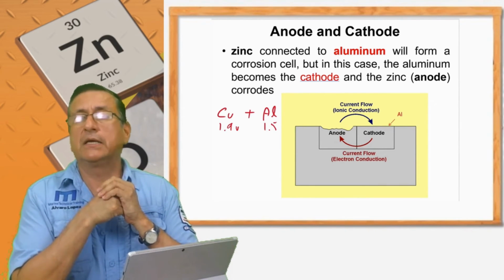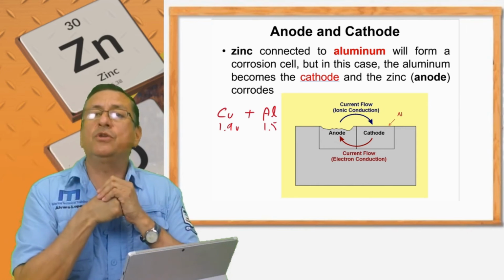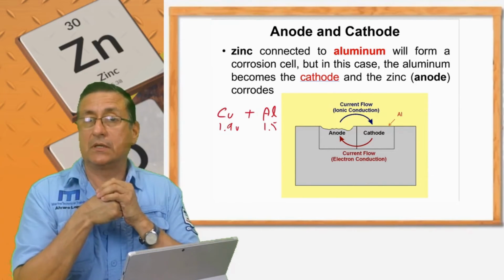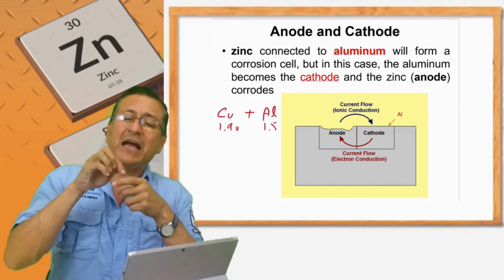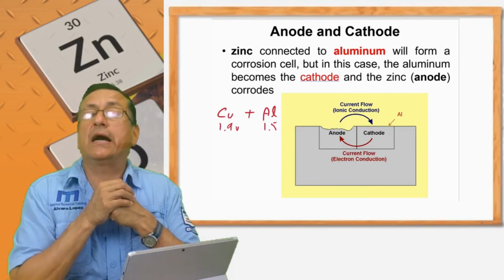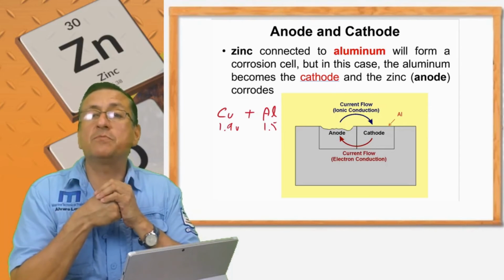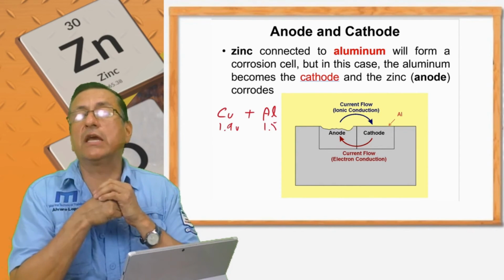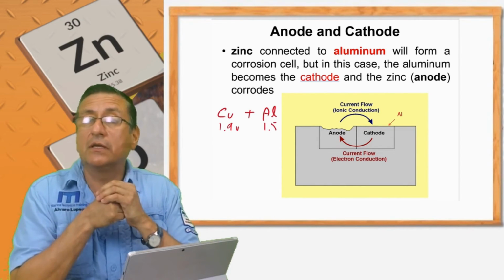For example, in an aluminum tank, when you use copper fittings, the copper fitting attacks the aluminum and erodes the aluminum around the fitting, and in 6 months, 1 year, you have a leak over there. This is catastrophic in a boat.